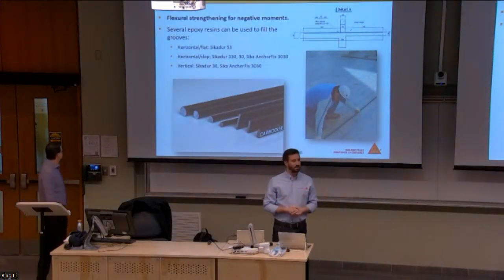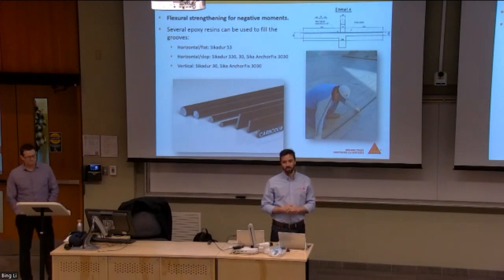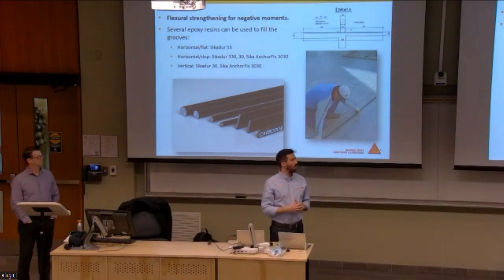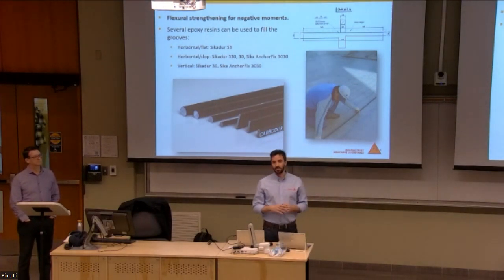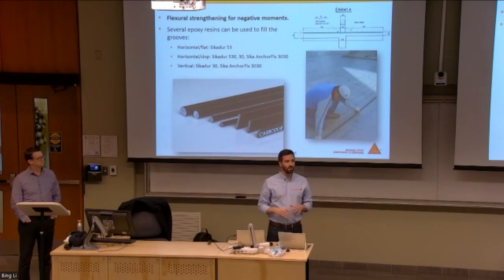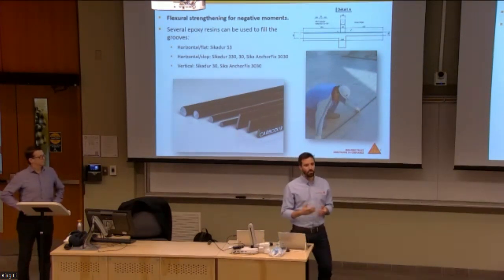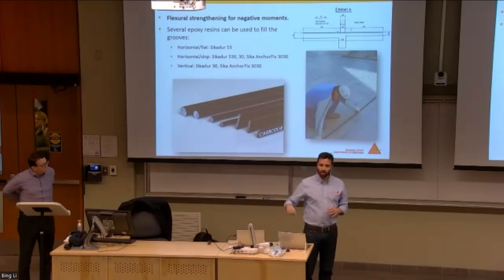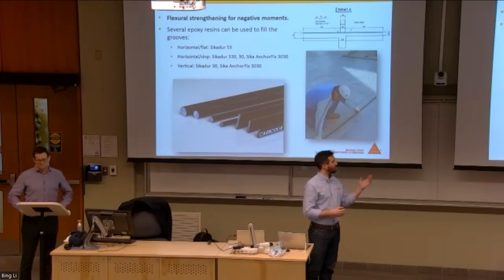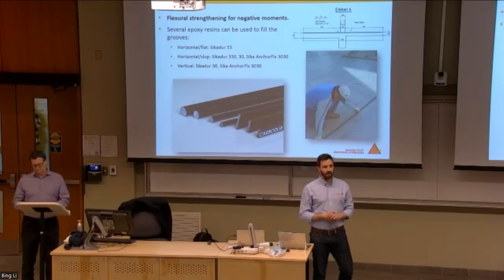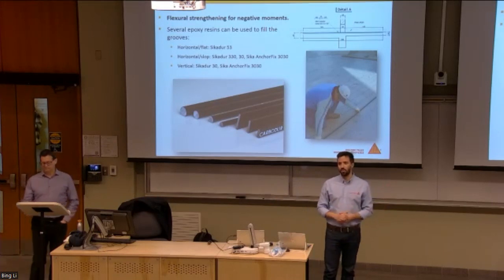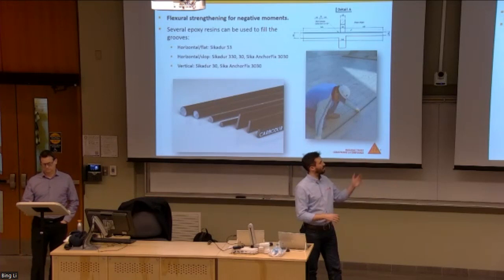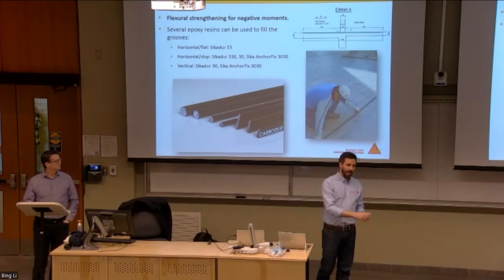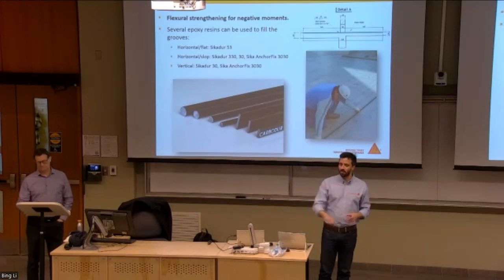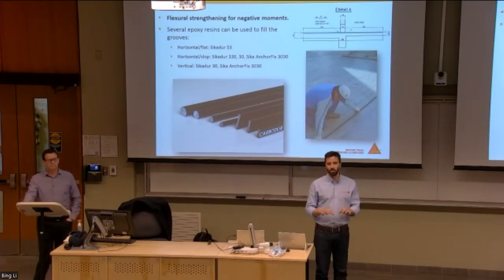The most important thing with this system is that you are going to be in the concrete. So that's the beauty. Instead of having a large surface preparation to install CarboDur plates or Sika Wrap fabrics, here you are just creating a small groove into the concrete, and then you can fill the groove with one of our epoxy materials. At Sika, we have plenty of options as epoxy resin. If you are working on a horizontal and flat surface, we have a low-viscosity resin that can be poured into the groove after you install the CarboDur rods.